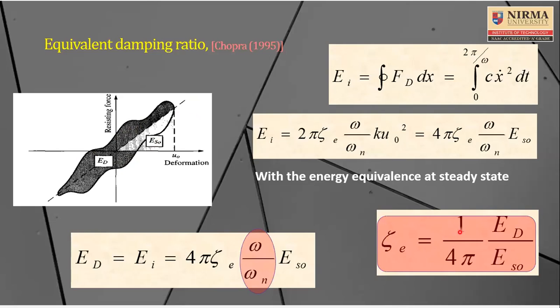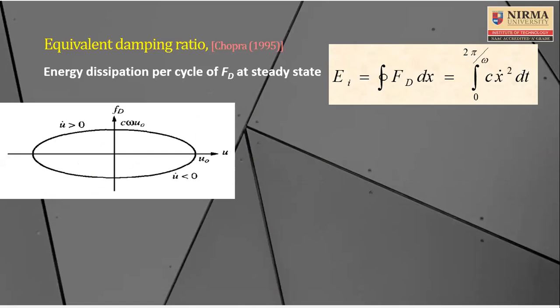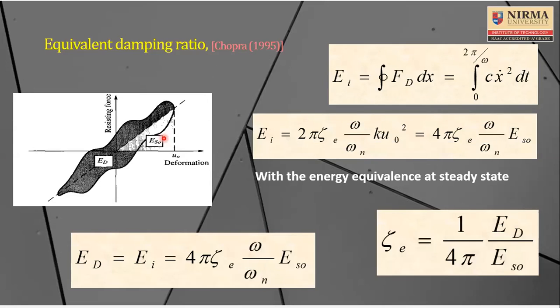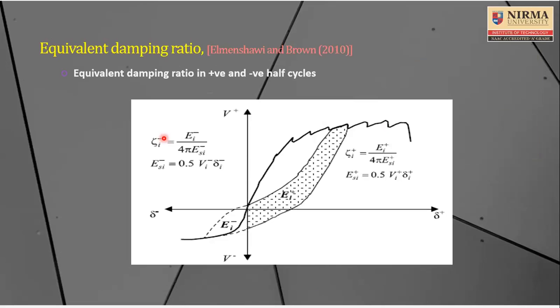Therefore you will be able to calculate the damping coefficient by a simple equation of 1 upon 4 pi, which is a constant, times Ed by Eso, where Ed is the energy dissipated in a real experimental setup made from whatsoever material, and Eso is the corresponding energy dissipated by a viscous damper, and therefore you can very well calculate the equivalent viscous damping ratio.